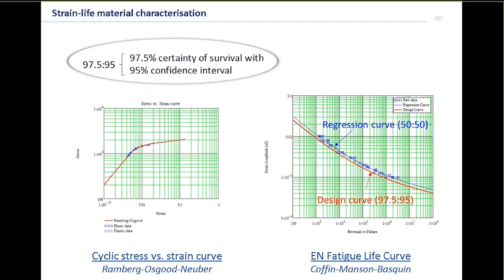But the other thing is, most FE users will do a linear analysis in FE even though there may be some local constrained plasticity. So we'll probably want to use something like Neuber's rule to turn that linear measurement from FE into an elastic-plastic measurement for this. And again, that cyclic stress strain curve allows us to do it.